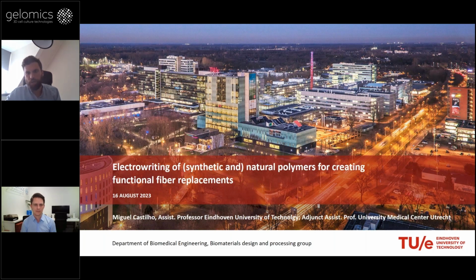Yeah, no, I agree. If that is the question, yes, it's also an important property. Of course, for MEW, you need to consider other properties, as I mentioned, like the conductivity, that are also important. And here, the shear thinning, and I would say the speed by which your fiber solidifies, is way more important than in extrusion-based printing, because since you are combining two forces, you are accelerating your jet 10 times faster. So you actually need your material to solidify way faster than in extrusion-based printing. And then, of course, in extrusion-based printing, there are all the tricks of printing in a support bath that basically allow you to print also with liquid-like formulations that do not have any shear thinning behavior. Fantastic.